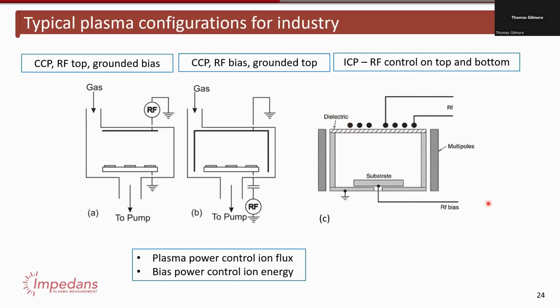Another method is applying more than one RF bias to the substrate. You could apply a low frequency and a high frequency. The low frequencies elicit more response from the ions, so you can get much higher energies, whereas the high frequency is mainly delivering plasma density. So that somewhat separates them out, although it's more complicated to build a tool that way.